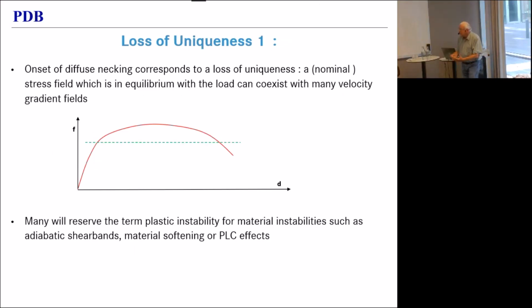Now, not everybody, as I said before, calls it instability. If we look at necking, and in particular diffuse necking in a metal, people will usually identify that with a loss of uniqueness. And clearly, if you look at the force displacement curve for a tensile test on a piece of steel, the necking starts in the maximum. And once you are beyond necking for a given force, you match two displacements. So you lose the uniqueness of your solution. And at the very minimum, when you do an implicit solution, that may cause problems.